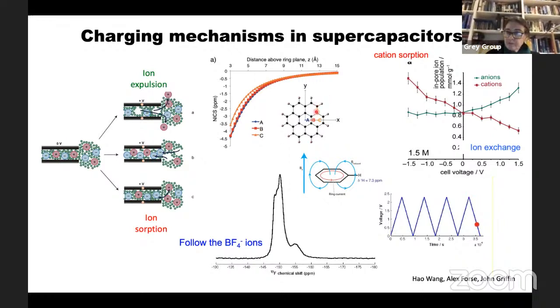And so this is now an experiment where we're charging both positively and negatively, and we're quantifying the intensity of this signal. And based on that, we can show that when you charge positively, you have an ion exchange mechanism where anions go in and cations are kicked out. But when you charge negatively, actually only the cations go in. And that's because they have a preferential adsorption with the carbon. Okay, so what about this shift of this peak? So it's going backwards and forwards. Here, this is when the carbons are the most aromatic. But when you put in electrons or you put in holes, you reduce the aromaticity, and so you get a shift. And so you can understand things about the electronic structures of the carbons as well.